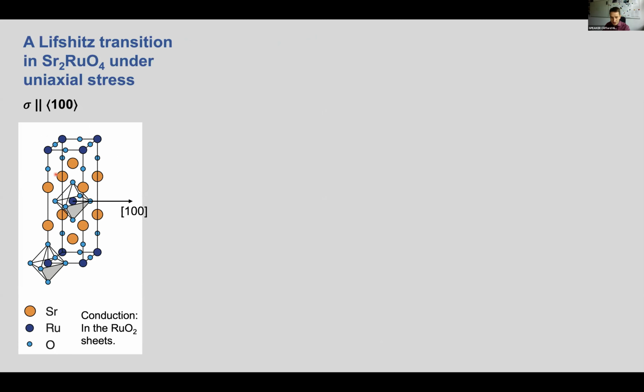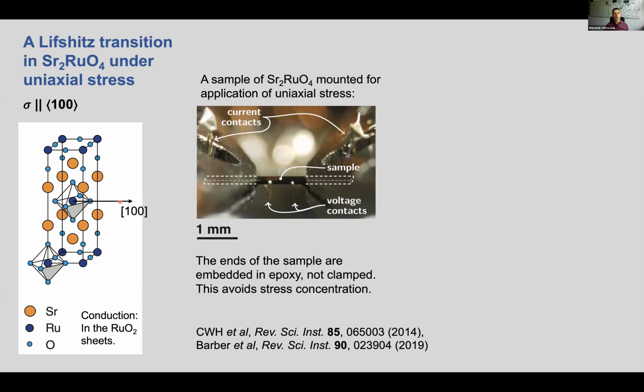Okay, so now to talk about strontium ruthenate. So this is the lattice structure of strontium ruthenate. It contains ruthenium oxide sheets separated by strontium oxide spacer layers. And the conduction occurs within the ruthenium oxide sheets. So it is a highly two-dimensional material. And we're going to be applying stress along the 100 direction, along the ruthenium oxide bond direction.